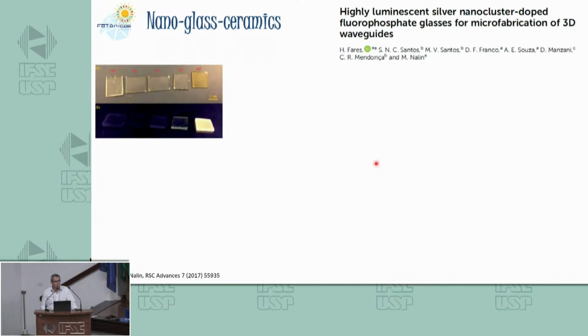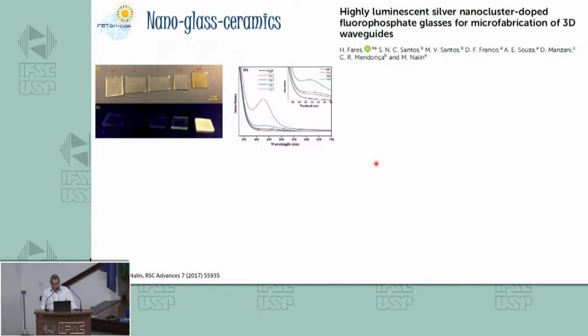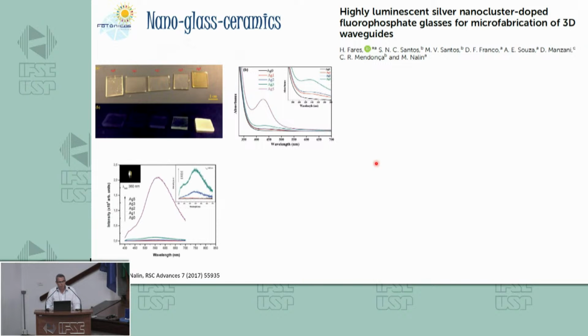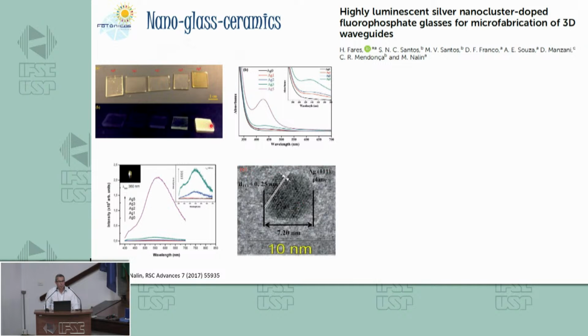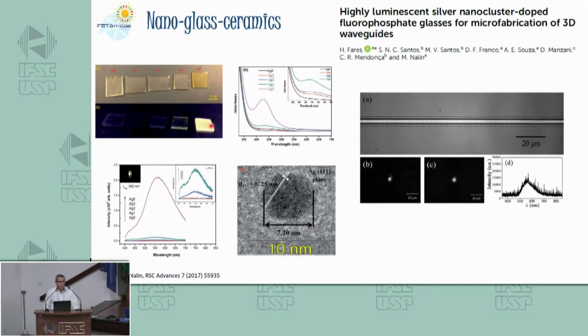This is another one. We did the same, in the same direction. We controlled the size of the nanocrystals by changing the composition. And in this study, we had a composition that presents a very good white emission. And then we use another technique that is laser writing, okay? Using femtosecond lasers, we can inscribe a channel inside a glass, not on the surface, but in the middle, below the surface, by controlling exactly where the focus of the laser will be.